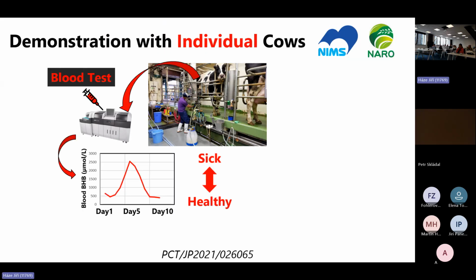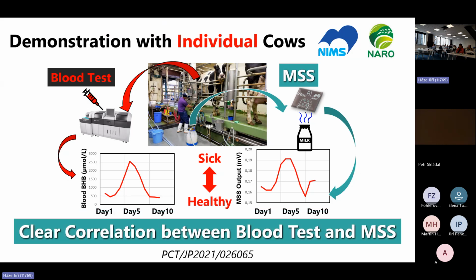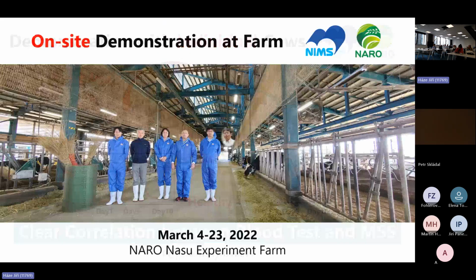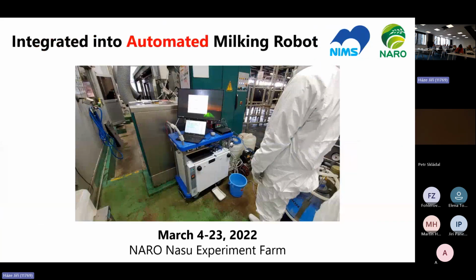We made a blood test, and some specific cow got sick and recovered. Meanwhile, we also measured the smell of milk with our sensor, and we confirmed that we can clearly monitor this trend. So we tried to make this kind of time series individual measurement at a real farm. We went to an actual farm for 3 weeks and tried to make these measurements. We constructed our own automated milking measurement system working with the milking robot behind.